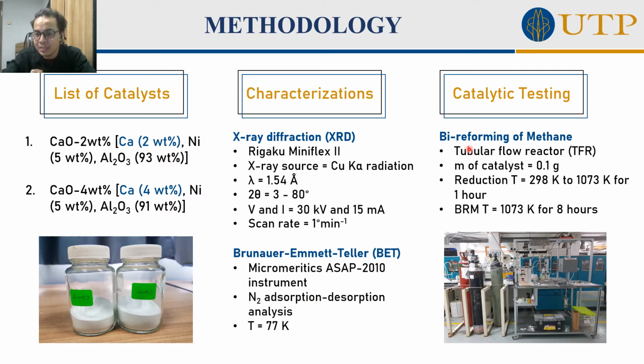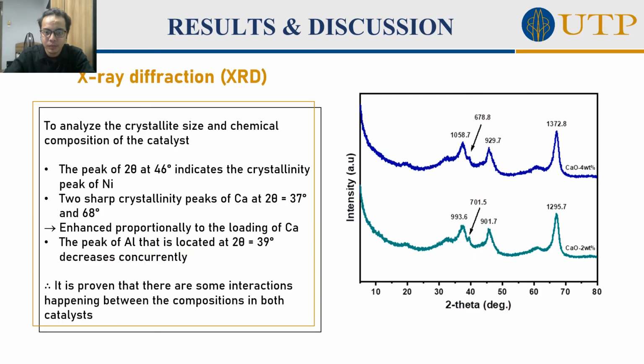And the last one is catalytic testing, where we have employed bi-reforming of methane to examine our catalyst in a tubular flow reactor. The mass of catalyst that I've placed into the reactor is 0.1 gram, with the reduction temperature from 298 Kelvin to 1073 Kelvin for 1 hour, and the reforming temperature is 1073 Kelvin for 8 hours. This is the picture of the tubular flow reactor that I've utilized. Next, I will proceed with the results and discussion for this project.